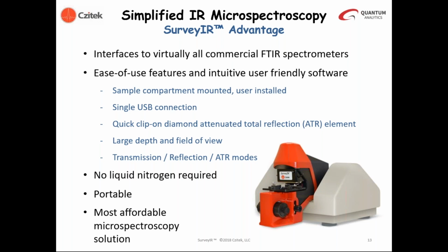We have a clip-on diamond attenuated total reflection element that makes it particularly easy to analyze many samples using infrared spectroscopy because you simply touch the sample with a diamond crystal and measure the spectrum by contact. Also different in this system versus other FTIR microspectroscopy systems is that we have a very large depth of focus and field of view, which makes it easy to locate samples. And it has a lot of power associated with a relatively low-cost device, in that we can analyze samples in transmission, reflection, and attenuated total reflection infrared modes.